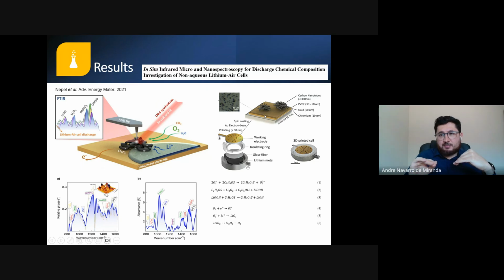really well polished. We have a roughness of less than 50 nanometers here. And then we disperse carbon on the surface, and then we use IR to understand this process. So IR is very sensitive to organic electrolytes. And in this case, we also could see DMSO forming and decomposing, and you have some intermediates forming in the process. It was really useful to understand how the electrolyte works.